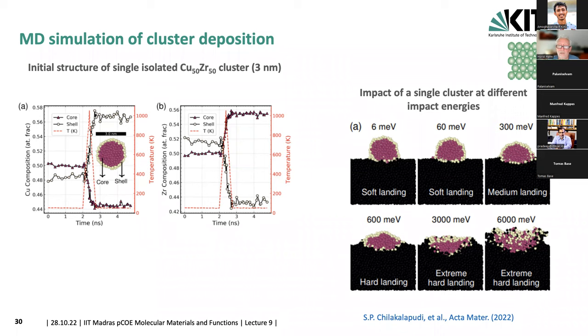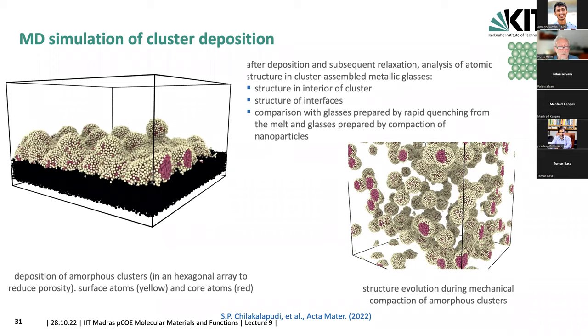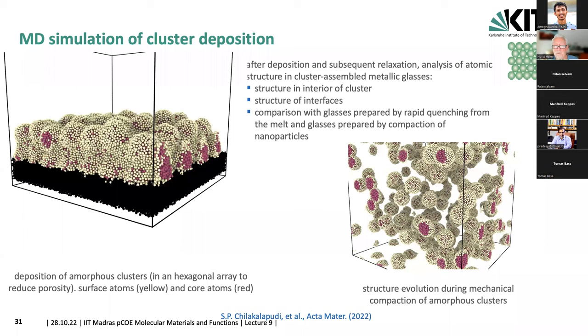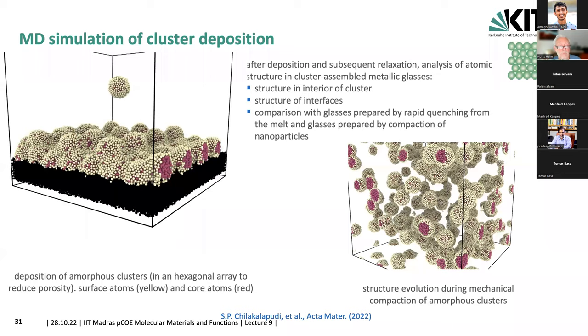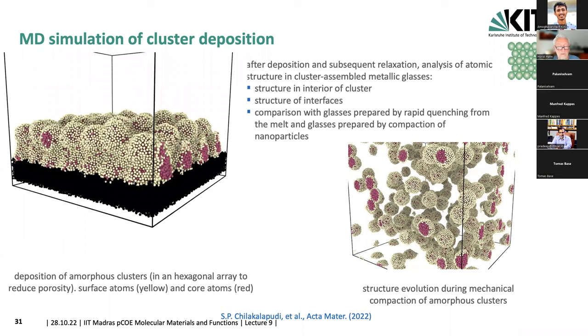So this is a video which shows, and we have chosen an array which would not represent exactly what we see in the experiment, because here we have chosen that the clusters land in a hexagonal array. We just wanted to optimize the formation of the interfaces, but other than that, it's a fully realistic simulation.